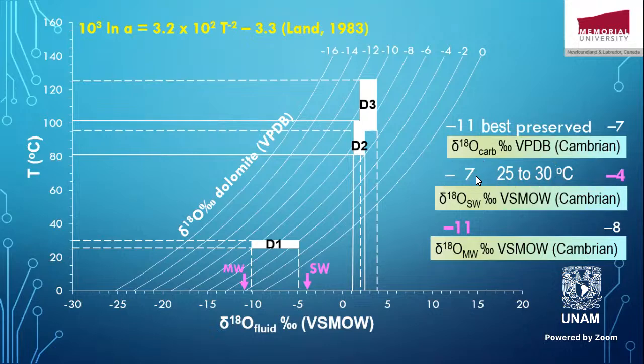We found that the seawater should be around that time between -4 and -7. Well, in our present day tropical environment, and these sediments that we are looking at seem to be a really tropical environment, the rainwater is usually about 4 per mil lighter than that of the seawater. And this means that the range for the meteoric water during the middle upper Cambrian was between -8 and -11, because -4 and -4 should be -8, and -7 and -4 should be -11. Now take the maximum, which is the most enriched signal of the seawater, -4, and take the most depleted signal coming from the meteoric water, -11.